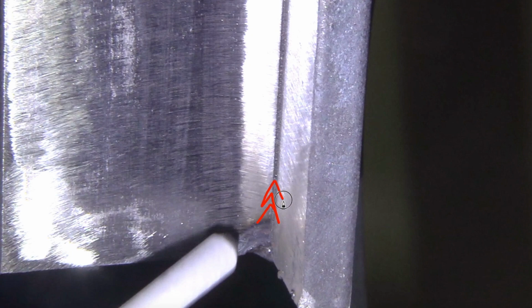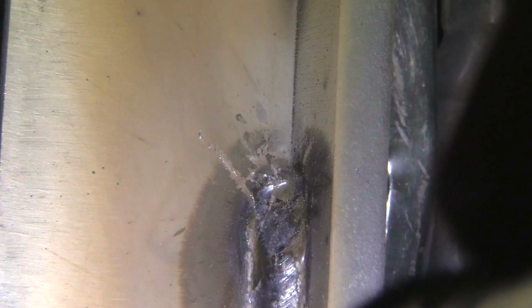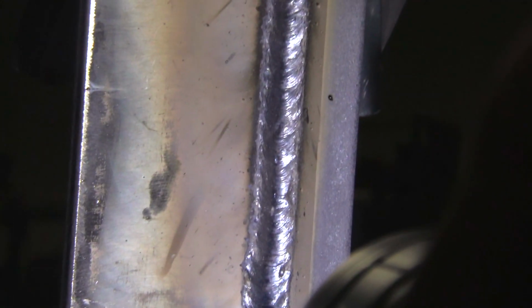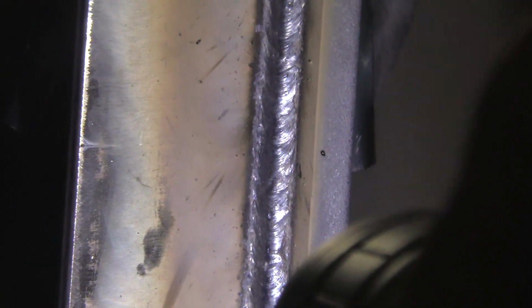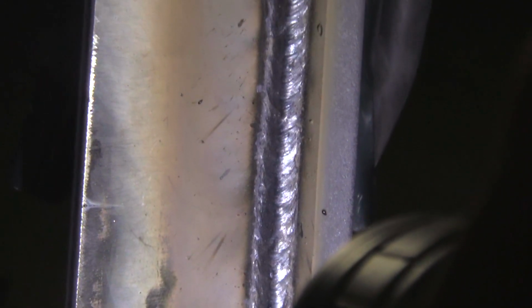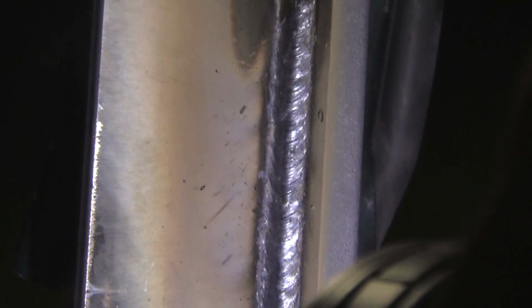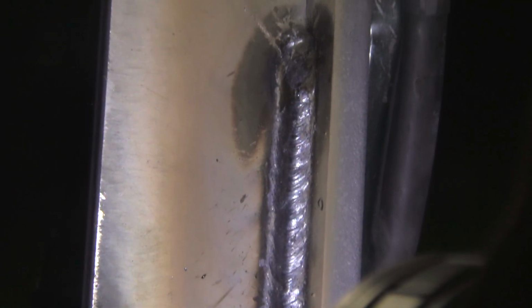Here's a little schematic of the technique used here. It's an upside down V, and coming back on those sidewalls tends to fill in any undercut there might be, and then going forward just keeps your arc on the leading edge of that puddle, keeps you getting penetration into the root. All right, that's one rod down. Before we do the restart, let's take a quick look and see how Andrew's doing here. I don't see any undercut, nice and uniform, slightly crowned but not excessively.